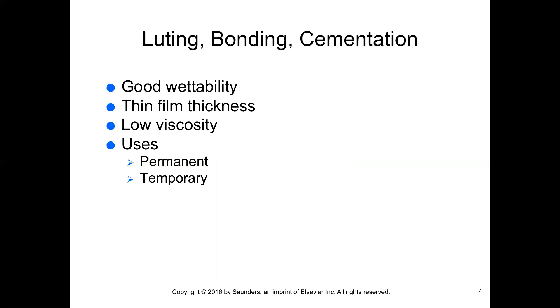If the viscosity of the cement is such that the prosthesis fails to regain intimate contact with the tooth, a thick layer of cement will be exposed at the margin. Viscosity refers to how well the material can flow under compression. When placing a crown on a prepped tooth, you can't have thick cement because it won't flow well — it will leave a gap and can make the crown sit higher than it's supposed to, causing the patient to hit that crown first when biting.